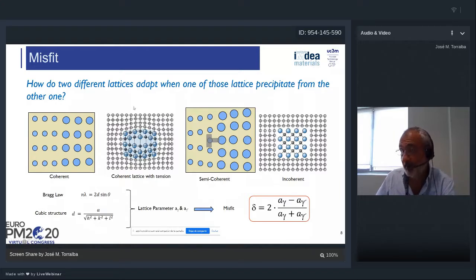Another interesting thing is that in the case of gamma prime superalloys, as much as we increase the incoherency, as much as we increase the misfit, the precipitates tend to have a more square than spherical shape.